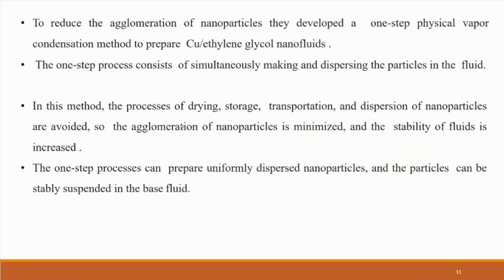To reduce agglomeration of nanoparticles, they developed a one-step physical vapor condensation method to prepare copper in ethylene glycol nanofluids. The one-step process consists of simultaneously making and dispersing the particles in the fluid. In this method, the processes of drying, storage, transportation, and dispersion of nanoparticles are avoided. So agglomeration of nanoparticles is minimized and the stability of the fluid is increased.